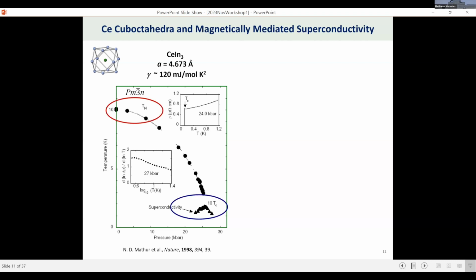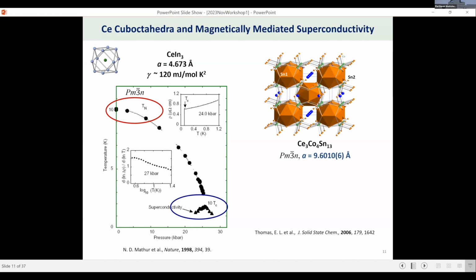And in fact, as part of that goal, we actually made this compound. We published it in 2006, and we were excited to see this because it reminded us of a perovskite compound. So this would be the first example of an intermetallic perovskite, which we were excited about. And if you look at the formula, it's ABX3, it's a triple perovskite. One of the Sn sites is on the A site.